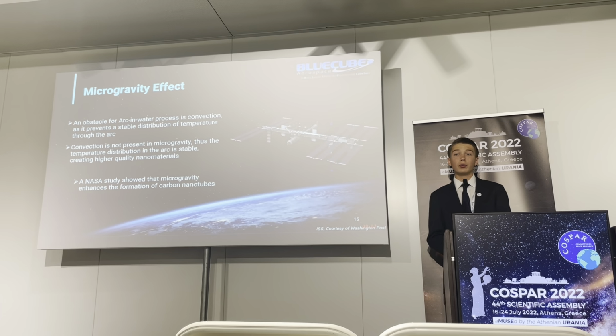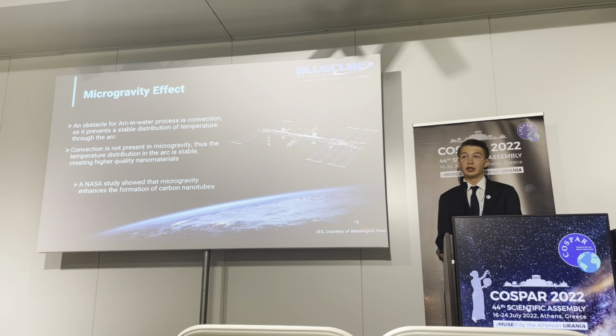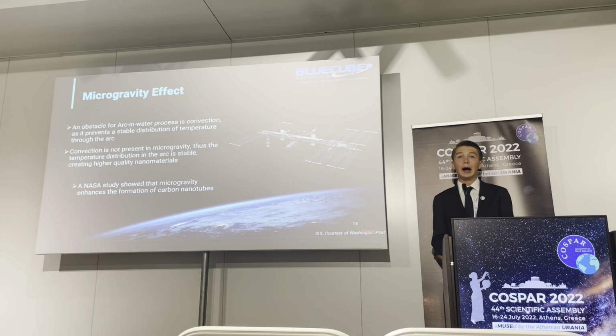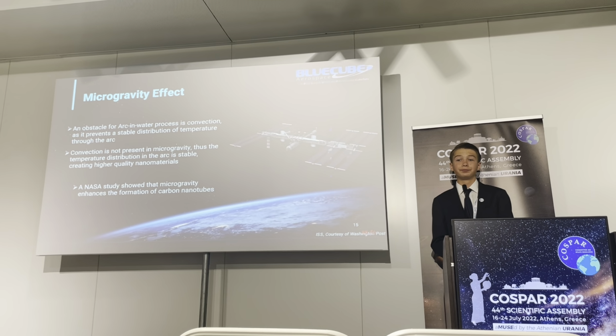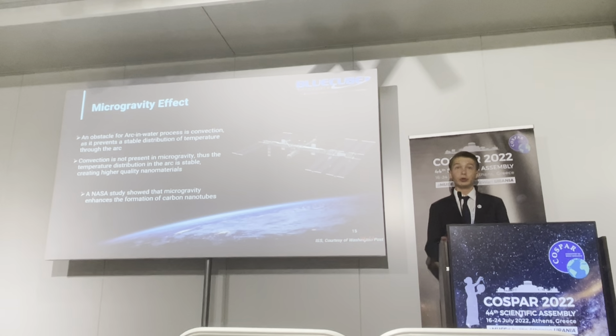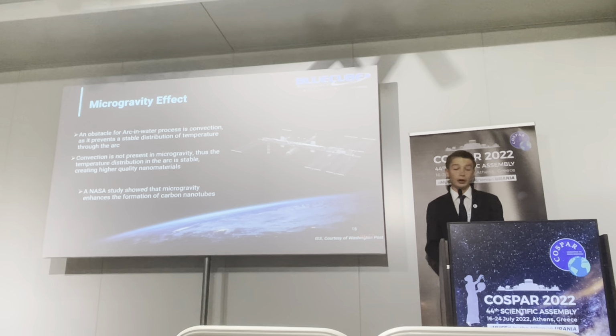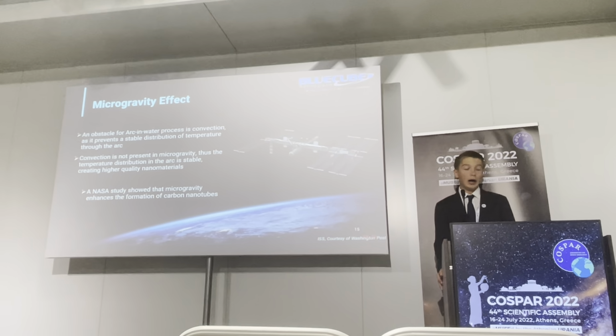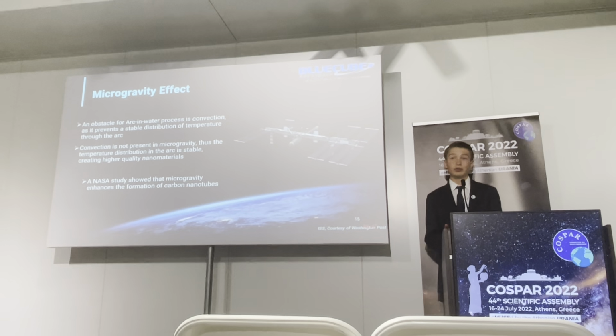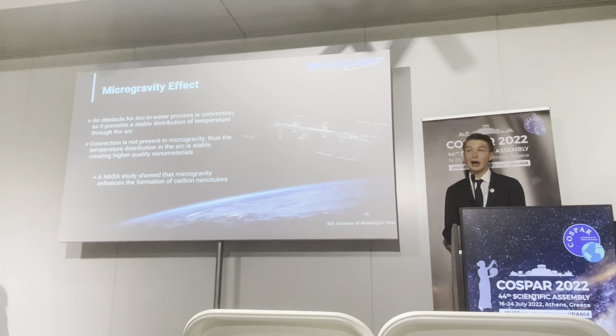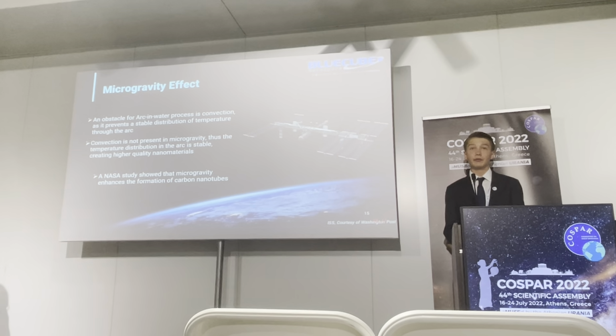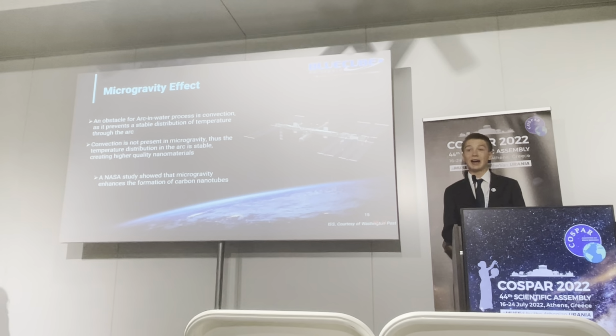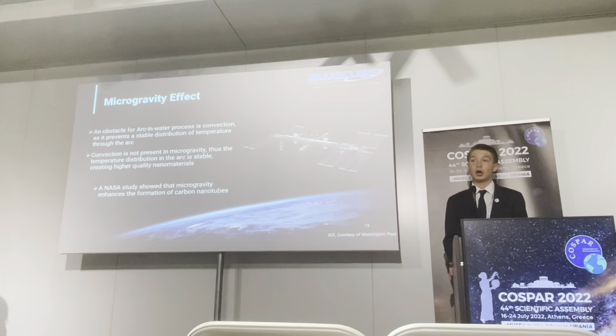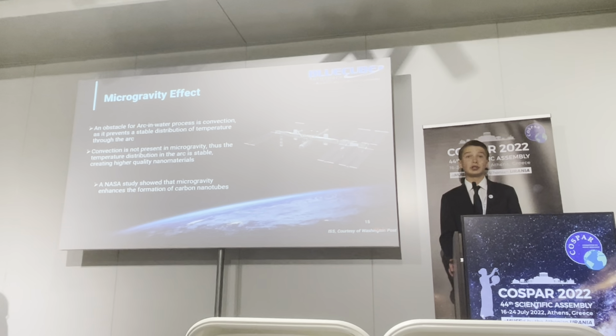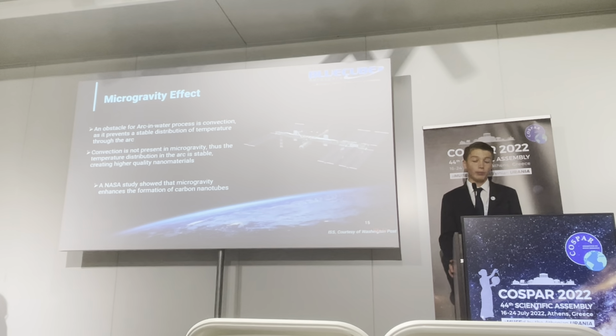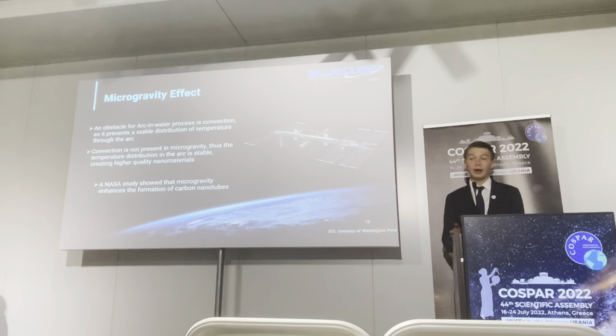However, in microgravity, where there are not as many forces acting on the water, it's much easier to create a stable thermal gradient, which then leads to better quality production of graphene. Recently a NASA study tried to quantify how much convection impacted the formation of carbon nanomaterials in the arc in liquid method, and see how microgravity could help that.